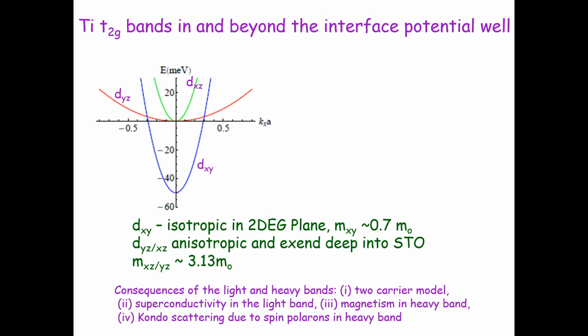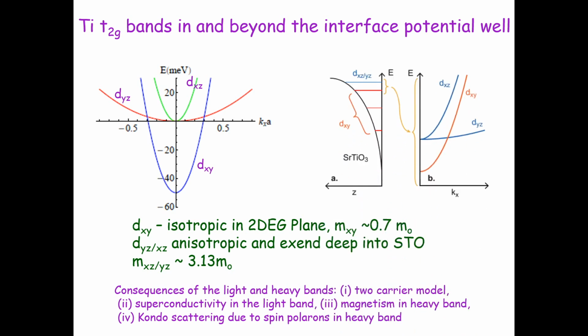Okay. Now, what happens at the interface? The interface, this is your triangular quantum well, and you start filling it. So first is this guy. So these are confined levels of this dxy in the quantum well. If the Fermi energy is somewhere here, then the extended view of this is here. So first you will fill the dxy, and then you start filling yz and zx. And it turns out that these guys are the so-called low mobility carriers. They are large in number, and these are the electrons which fall in yz and zx. These are the so-called high energy, high mobility carriers, but their number is small. That is our interpretation.